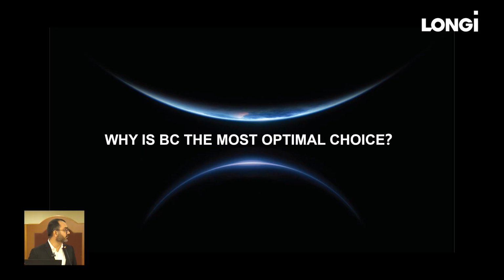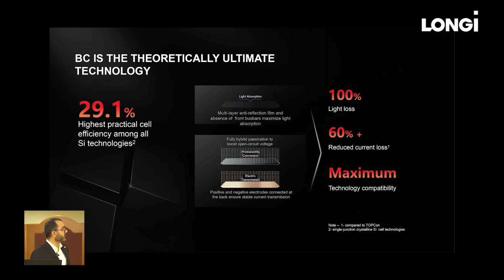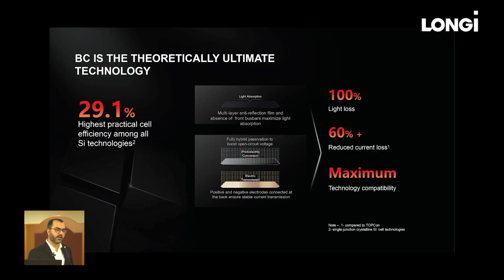So why is back contact the optimal choice? The most important part is the theoretical maximum efficiency of back contact, which is 29.1%. This is the highest among all the crystalline silicon technologies. Apart from having the highest efficiency, we have 100% light loss reduction.